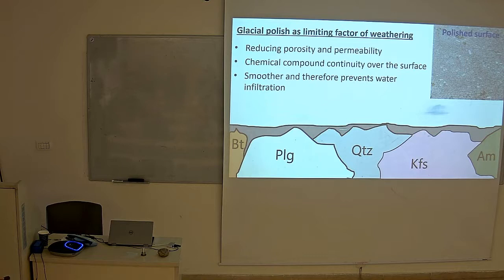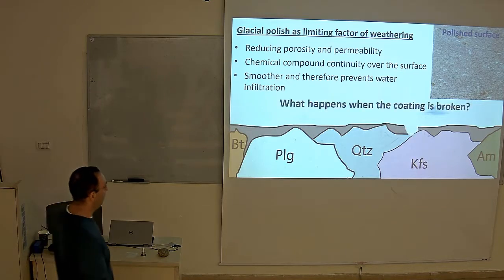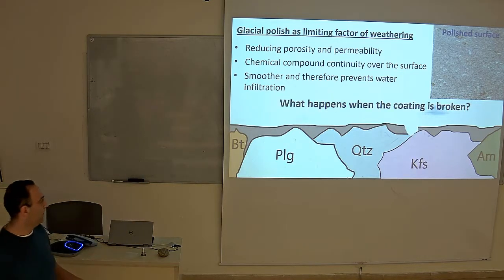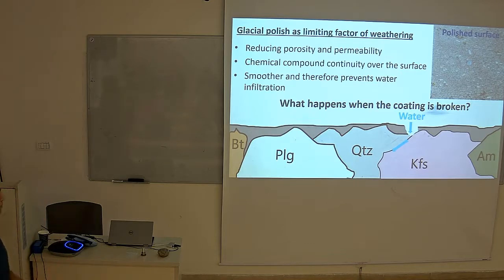This layer, the brown layer, is the coating. It's reducing the porosity and permeability, and therefore less water can get into the original crystal. The chemical composition of the material is actually the same over the surface, and there is no differential weathering of different minerals. And the surface, as was suggested in the same paper that I showed before, is smoother, and therefore water can flow faster on the surface. However, when there is a break and there is a hole, water can enter into it and start the weathering process.